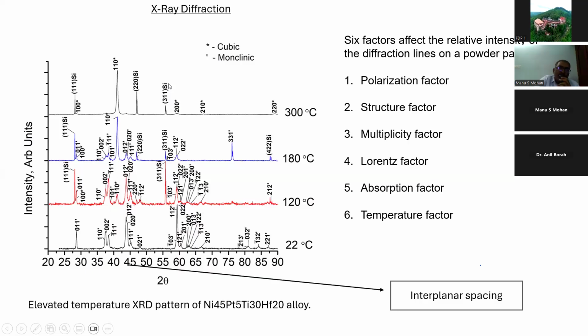You will see here some silicon peaks. What are those silicon peaks? Basically those are the peaks from the holder. Since these X-rays are captured at very high temperature, there is a high chance for background to come. Since it's a high temperature stage, we use alumina — normally we use glass, which is amorphous.